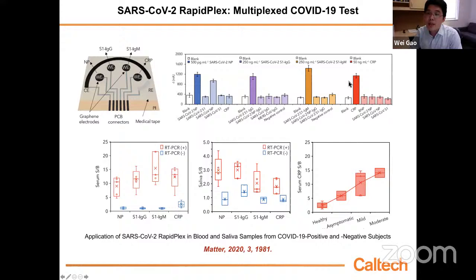And we did a test in COVID positive samples and COVID negative samples. We found that we can distinguish all the positive samples from negative samples we have, basically. So you see for NP, S1 IgG, S1 IgM, and CRP, all the levels we collected from both blood and the saliva are higher than the healthy samples.